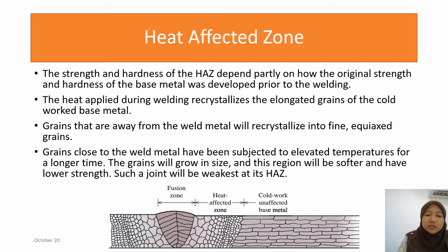So at the heat affected zone, the material receives sufficient heat or critical temperature that changes its properties. Okay, so those closer to the unaffected base plate normally appear in a smaller grain size, because at this point the heat is quickly conducted away to the base metal and dissipates quickly, thereby the grains that form are smaller because they do not have enough time to grow into a bigger structure.